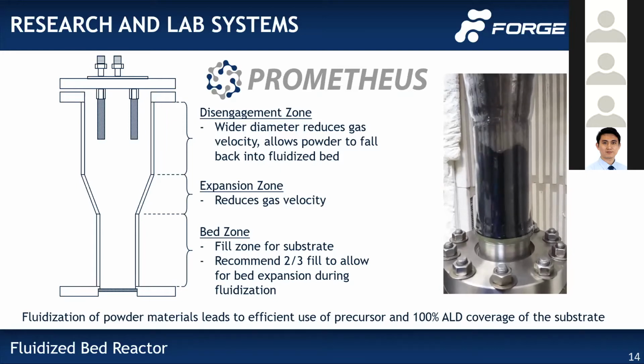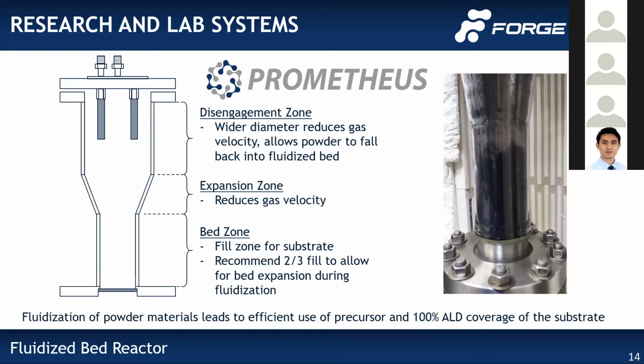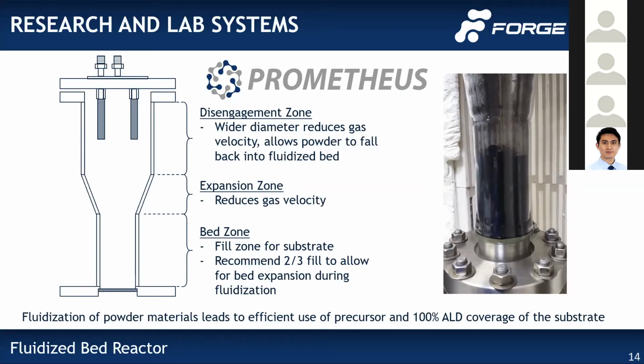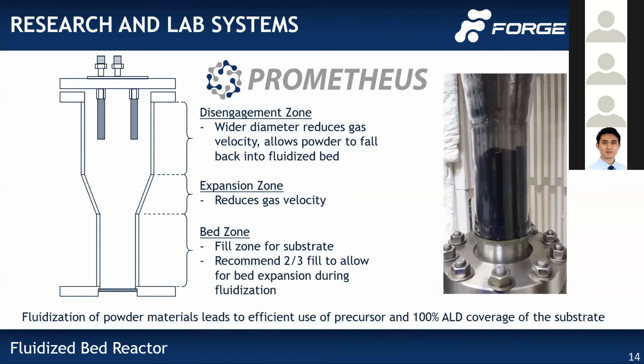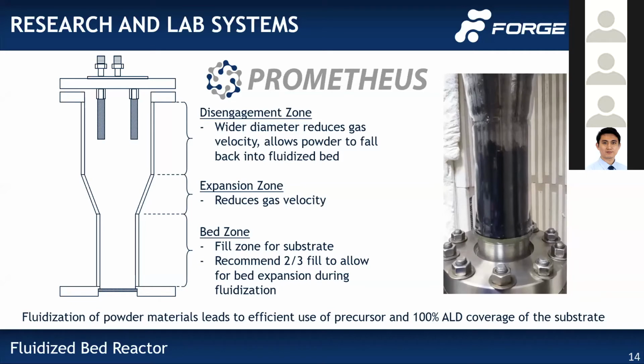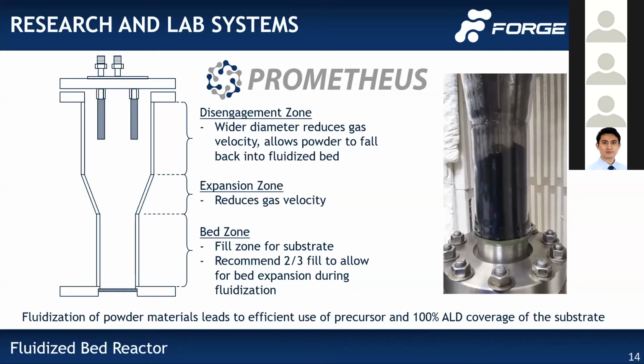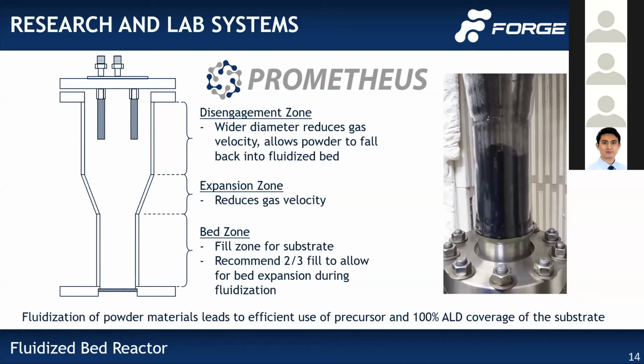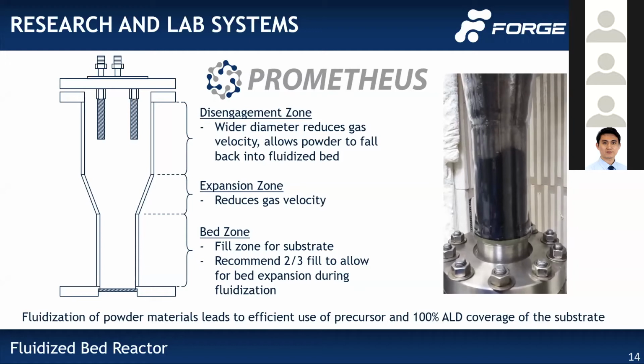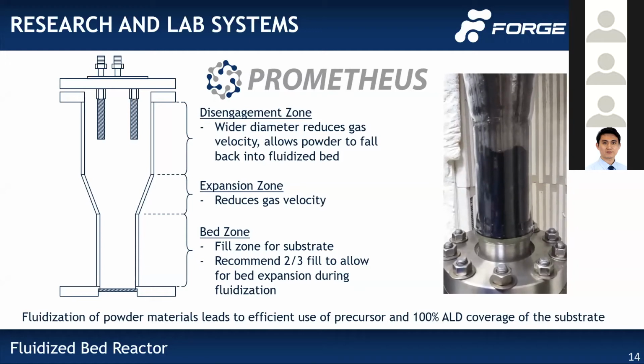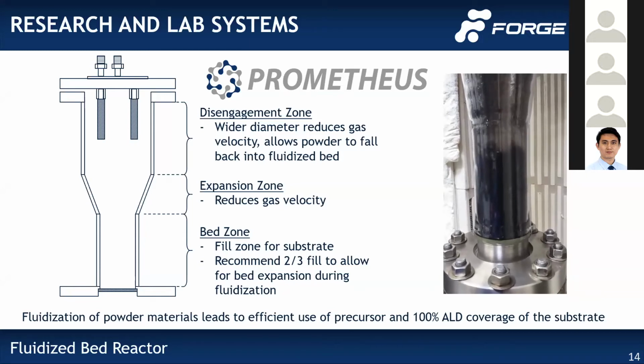These are really efficient for precursor utilization. For ALD, we can get nearly 100% utilization and 100% coverage of the substrate surface in a fluidized bed. Again, precursor utilization, we can have 95% utilization of a platinum precursor, which is very important if you are doing platinum deposition. Platinum alone is very expensive. Precursor is even more expensive.